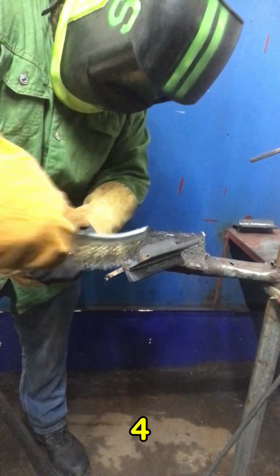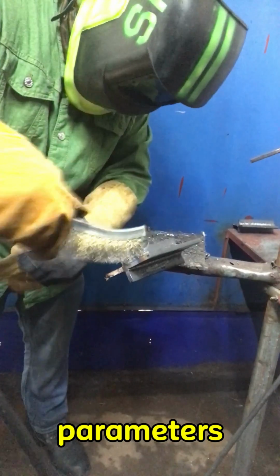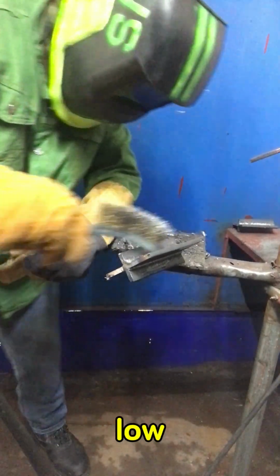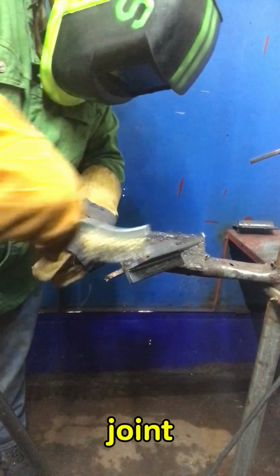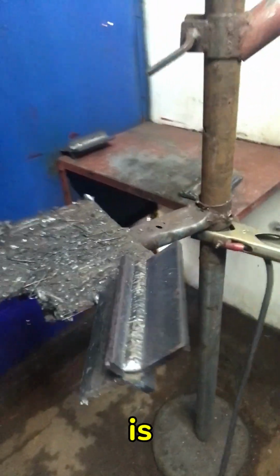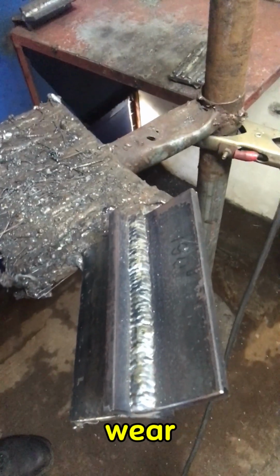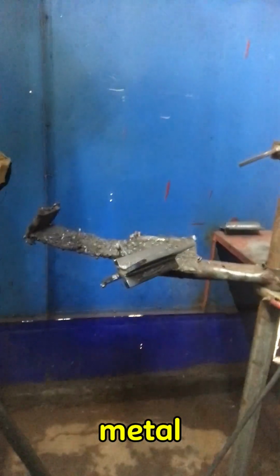Mistake number 4. Running incorrect machine parameters. If your heat is set too low, your filler metal lands cold on the joint, creating cold lap or lack of fusion at the toes. If your heat is way too high or your arc is too long, you end up with undercut where the arc gouges a trench out of the base metal that isn't refilled by filler metal.